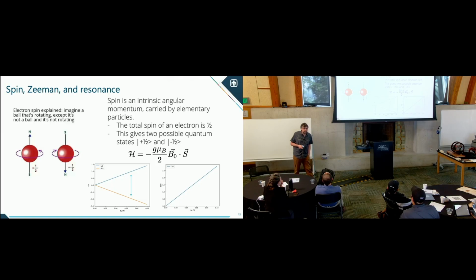So, of course, we know that a spin is intrinsic angular momentum, which is carried by elementary particles. And the total spin of an electron is defined by a spin 1/2, and it gives two possible quantum states. So you have plus 1/2, minus 1/2, and the energy of that is the Zeeman Hamiltonian. It's relatively simple. You have a g factor, Bohr magneton over 2, and then you have the dot product of the applied magnetic field. I call this B0 from the magnetic resonance standpoint because it's typically the larger one. That's your bias field, and then the dot product with your spin state.